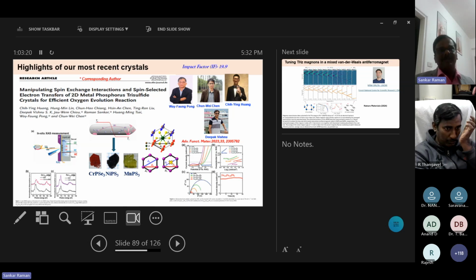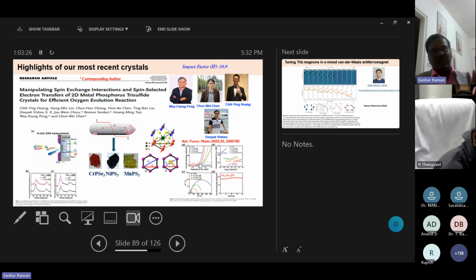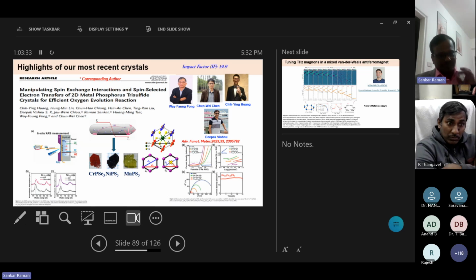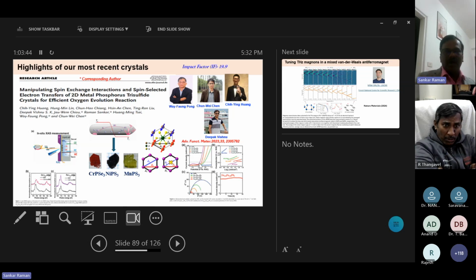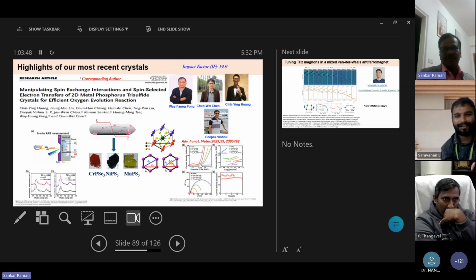In this material, once we dope the cobalt to enhance the high spin active center, the voltage is reduced from 1.6 to 1.4, which is an excellent oxygen evolution reaction material. And also we checked with XAS as well as XMCD, which clearly indicate that the magnetism is coming from the ferromagnetic nature, and we published this in Advanced Materials.